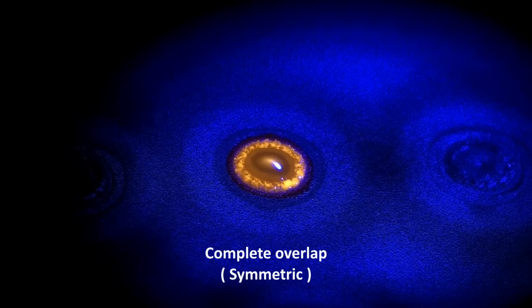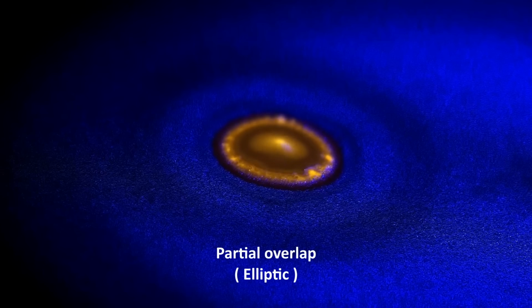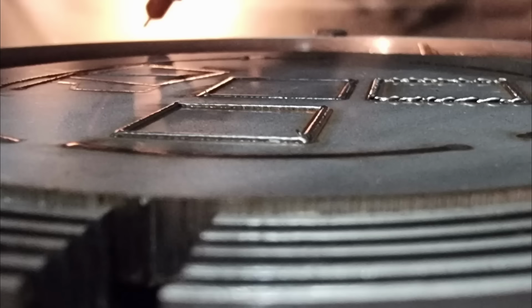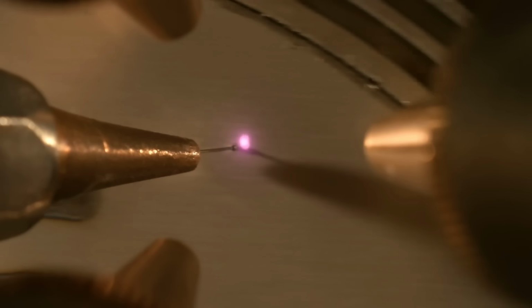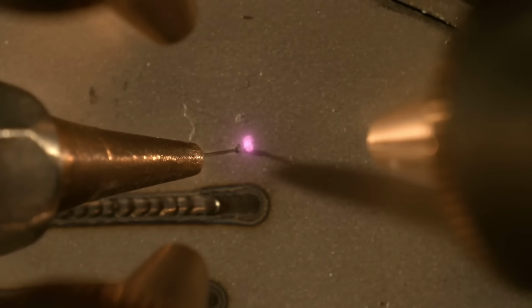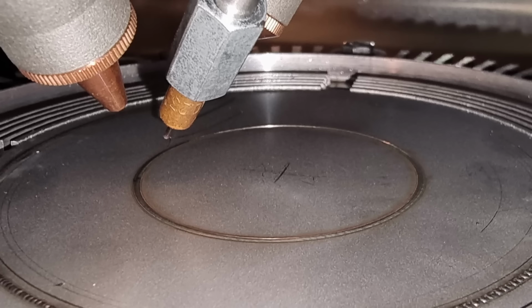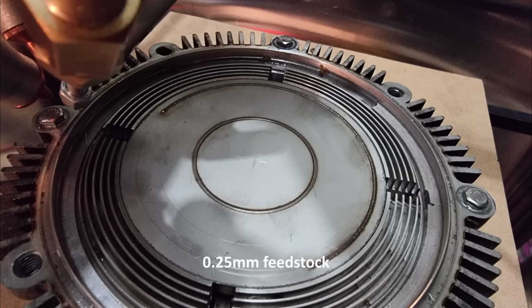The unfortunate thing about this design is that the layer height and respective track profile are influenced by the energy density, with the energy density itself being partially defined by the laser overlap and relative angle to the translation path, amongst other things. I would keep the beams partially overlapped to create a high point to aid beam deflection, and would also keep the wire fed at 45 degrees relative to the path of motion for the sake of simple geometric tests. But even so, this wasn't immune to reflections due to corners and other disruptions which would then build on themselves. Furthermore, if the platform wasn't exactly level, the degree of overlap would change and so too would the deposition height. But on average, with a level platform and a velocity of 10mm per second, a track width of 0.8mm and a wire feed rate of 22mm per second, this would yield a layer height of approximately 0.14mm.